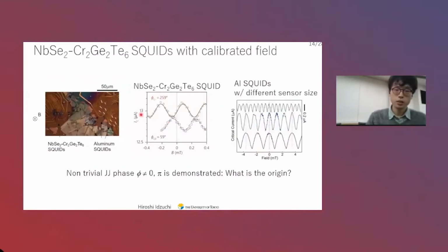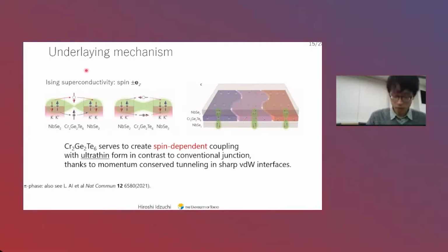And finally, we make this aluminum sample. So we have this niobium diselenide CGT SQUID, and also several aluminum SQUIDs, so that we know the exact zero field limit. Otherwise, it's very hard to distinguish the phase, because what's important is where the zero field is. By calibrating zero field with these several devices, we finally find the phase is neither zero nor pi, so it's very non-trivial. And then we had a hard time understanding why it happened, but finally we found how we can explain it.